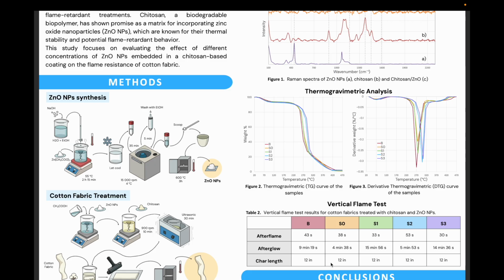For the thermogravimetric analysis, the thermal analysis revealed that zinc oxide improved the thermal stability of cotton. The most significant effect was observed at the highest zinc oxide loading, around 0.9 weight%, which shifted the main decomposition temperature by approximately 30 degrees Celsius compared to the blank fabric. This indicates that zinc oxide nanoparticles help delay cotton degradation under heat.